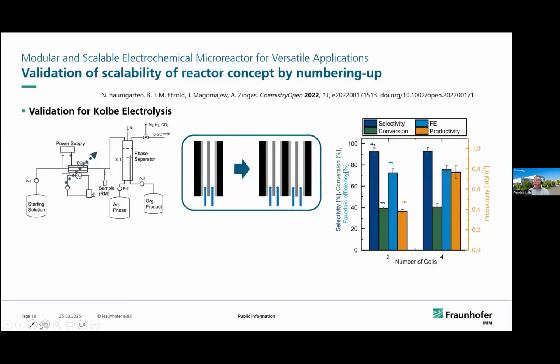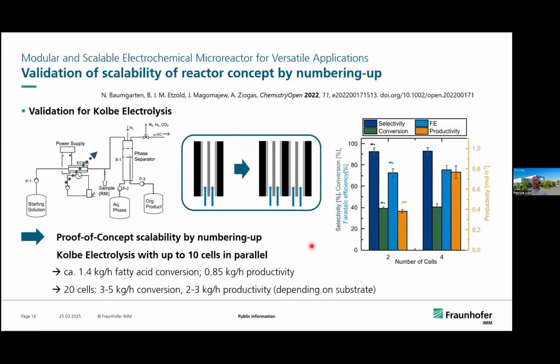We used in one experiment 2 cells, and in the other one 4. You see that the productivity increased by doubling the number, while all the other process parameters were kept constant, also Faraday efficiency, conversion, selectivity. This underlines the basic approach, also within the fatty acid idea, to use it there. To give you an idea about the scale we reached, we have tested up to 10 cells in parallel, and ended up with 1.4 kilograms per hour of fatty acids in the Kolbe electrolysis.